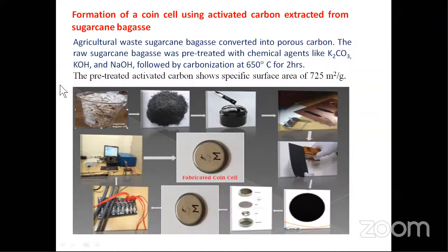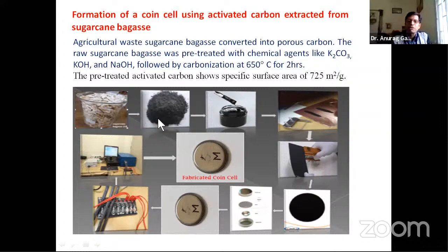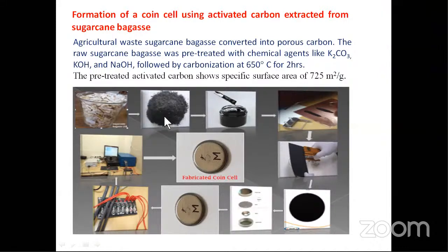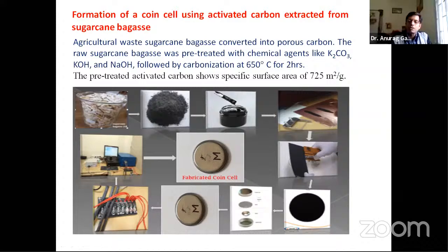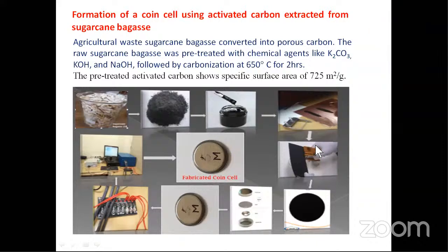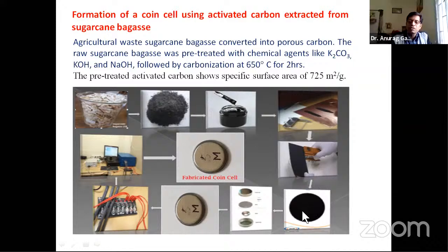So we made it a porous carbon. Firstly we make this porous carbon material, then we make the slurry. You have this powder material, and you can add carbon black: some 80% of this activated carbon, 10% carbon black, and 10% PVA, and you make this slurry. Then this slurry has to be coated over some current collector. It may be nickel foil or some graphite sheet, and you do the coating of this material. Then you cut it into the shape of a coin cell, because our purpose is that we want to fabricate the coin cell.